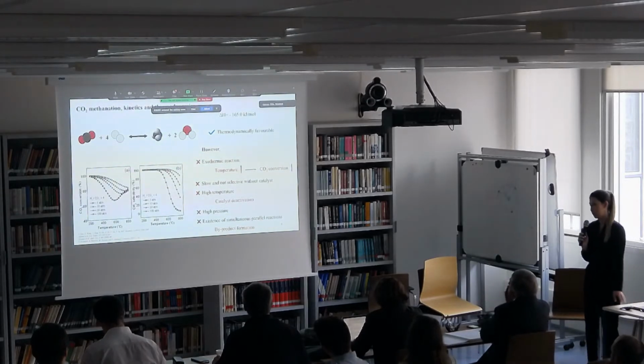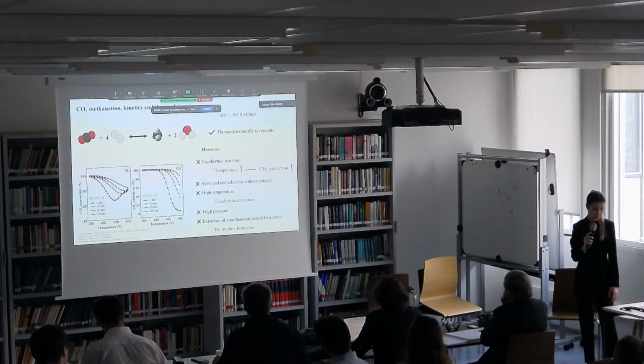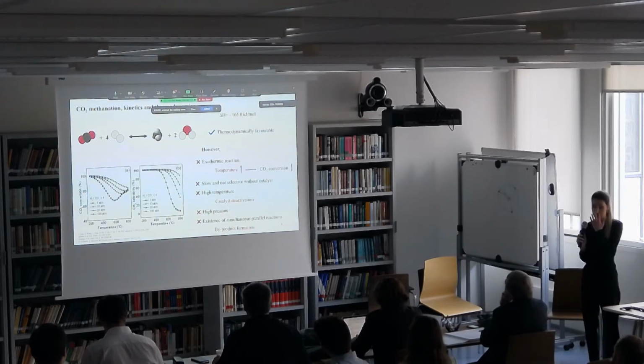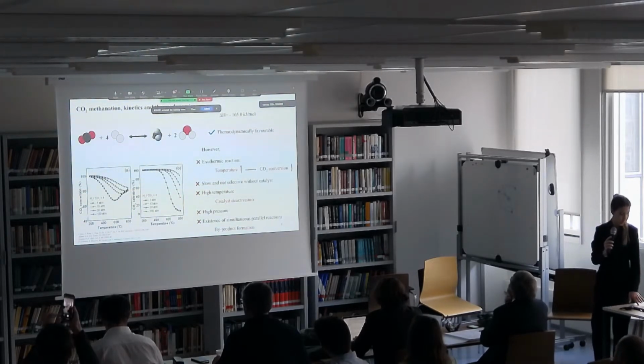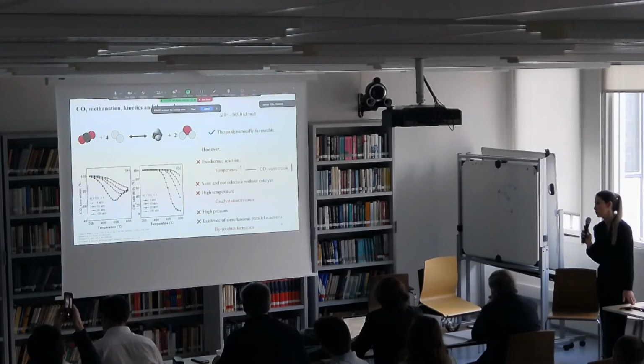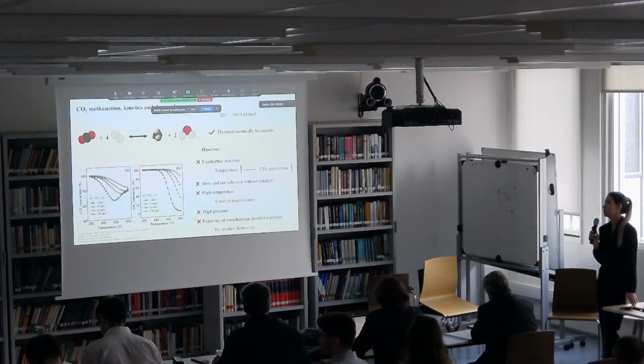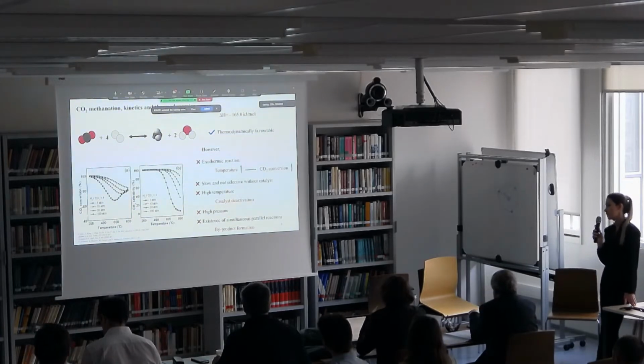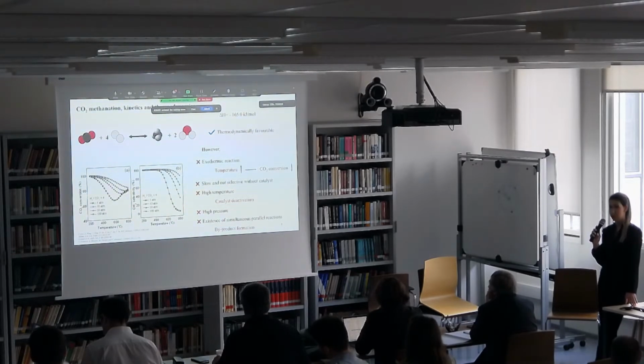However, in order to have the highest outcome of a product, it's important to know the kinetics and thermodynamics of a reaction. Methane can be produced by the reaction of CO2 hydrogenation, or Sabatier reaction. Sabatier reaction is thermodynamically favorable, but it has some disadvantages. As it can be seen, it's an exothermic reaction. So on one hand, at low temperature, the kinetics are not favorable. But on the other hand, at high temperature, the CO2 conversion decreases. Also, it's slow, and without a catalyst, you cannot really expect a high yield.